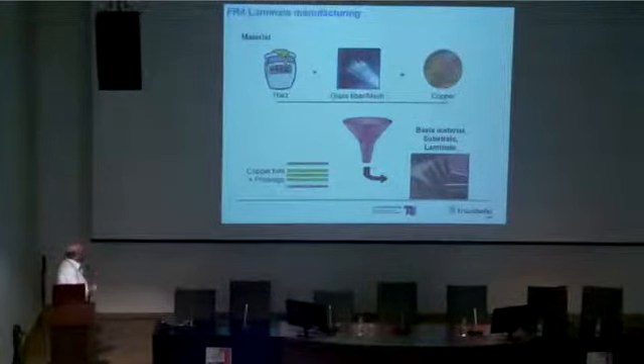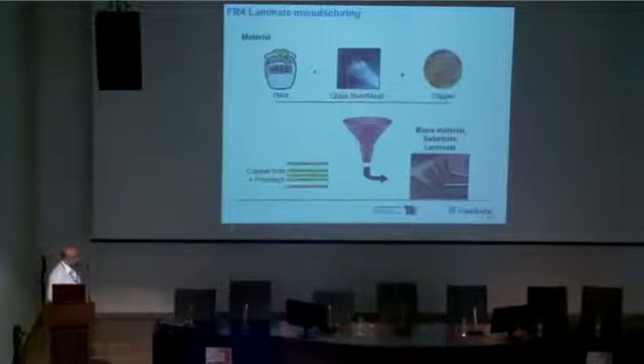Then what you do is you buy the resin. You have this very fine glass fiber mesh. You spend your nice euro. You buy copper foils that can come in many different thicknesses: 2 micron, 5 micron, 10 micron, 18 micron. Of course, you make sure that all the copper foils have the proper processing in order to increase the roughness of the copper foil before it is laminated on the prepreg. So you laminate the copper foils with the prepregs, and then you form this base material, as we say, the substrate, the typical FR4 material.